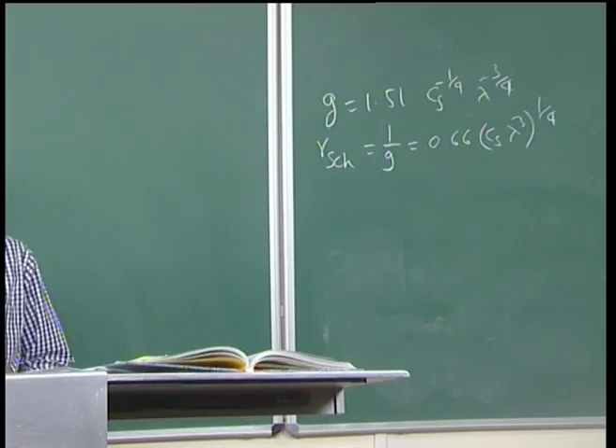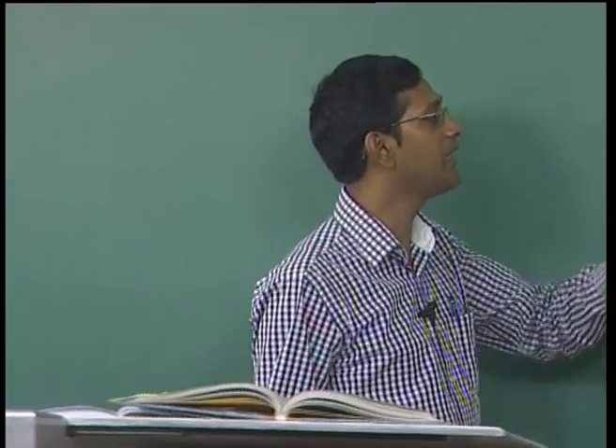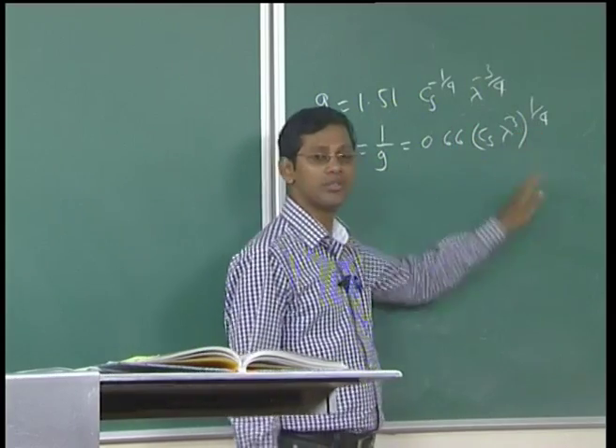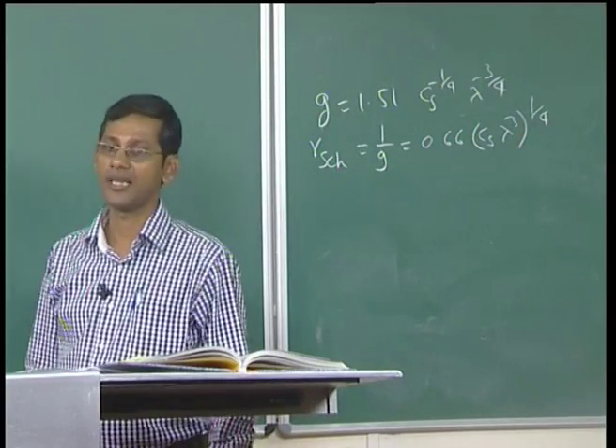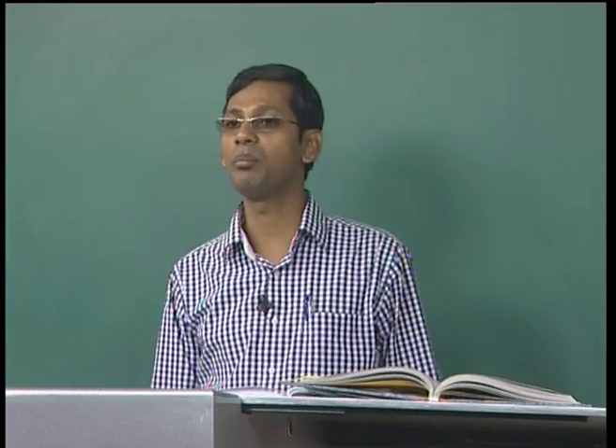That is why you now understand why people use million volt electron microscopes, because lambda can be exceedingly reduced by using higher and higher accelerating voltage. From 100 to 200, 300 kilovolts, people have gone up to 1.5 million, 1500 actually kilovolts.